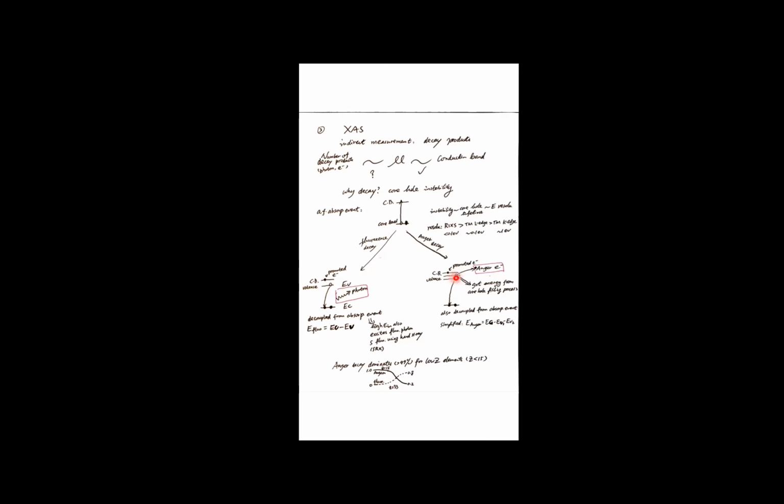So, okay, we see the core hole again, then it's not hard to imagine that this is not the end either, right? Indeed, this is not the end, and the Auger decay will be followed by other decay processes, which are more complicated. But let's just limit to the Auger decay discussion here. So it gives off an Auger electron, and the energy of this Auger electron can be roughly calculated by estimating the energy level of each electron involved, right? We have the core electron, valence electron 1, valence electron 2. Then the energy difference is what is gained by this Auger electron.